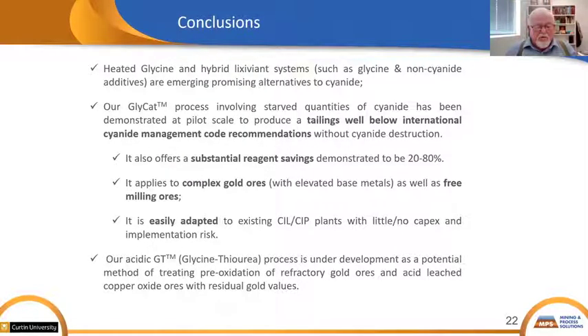Now for the whole paper in general, we can say that heated glycine and hybrid lixiviant systems such as glycine and non-cyanide additives are emerging promising alternatives to cyanide. The Glycat process involves starved quantities of cyanide, has been demonstrated at pilot scale to produce a tailings well below International Cyanide Management Code recommendations without cyanide destruction. It offers a substantial reagent savings demonstrated to be 20 to 80%. It applies to complex gold ores and those with elevated base metals, as well as free milling ores.